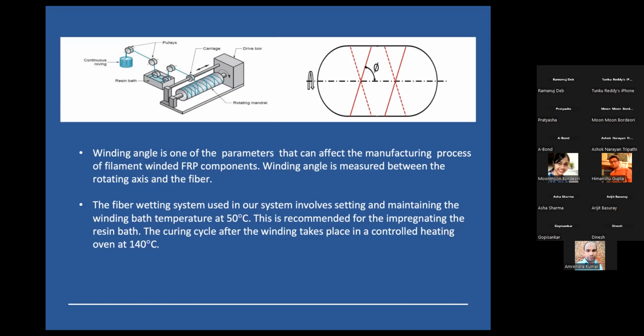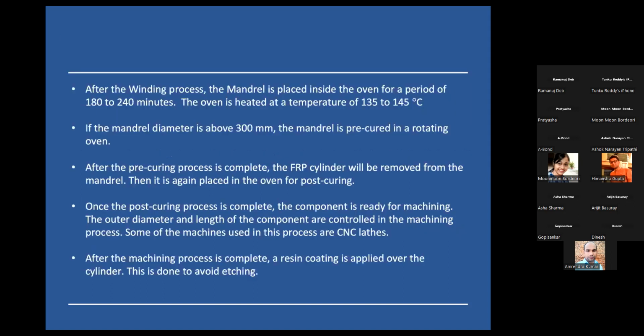The curing cycle takes place in a controlled heating oven at 140 degrees. After the winding process, the mandrel is placed in the oven for a period of 180 minutes to 240 minutes. The oven is heated at a temperature of 135 to 145 degrees. If the mandrel diameter is above 300 mm, the mandrel is pre-cured in a rotating oven. After the pre-curing process is complete, the FRP cylinder will be removed from the mandrel.